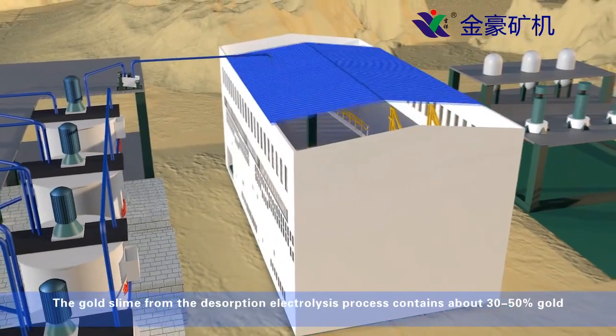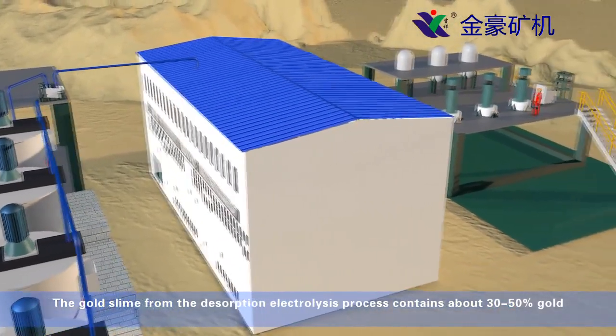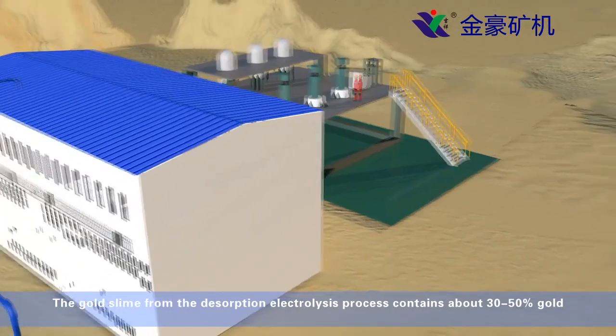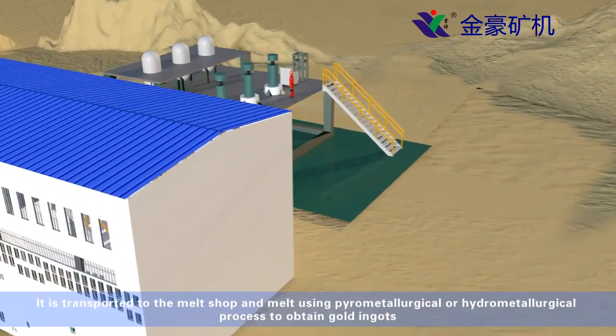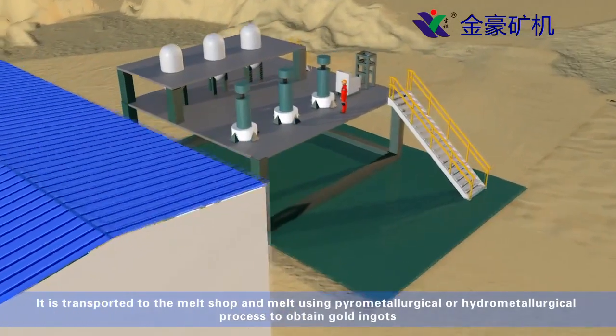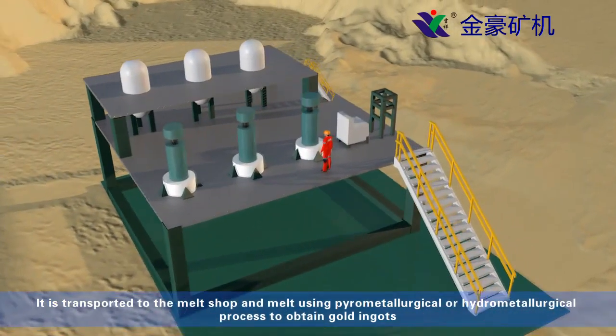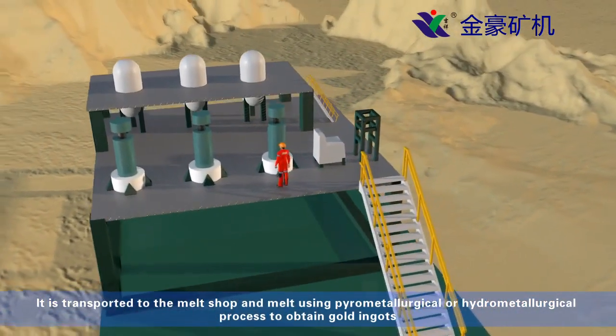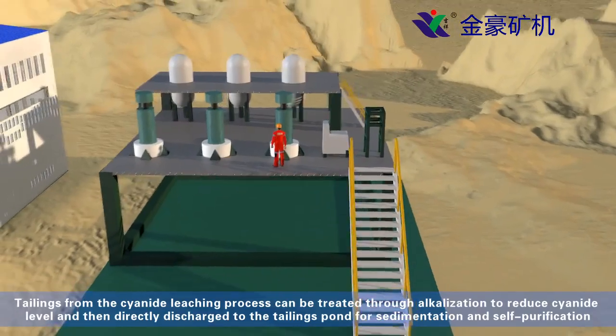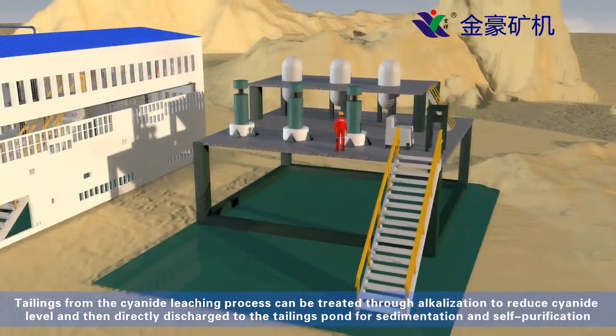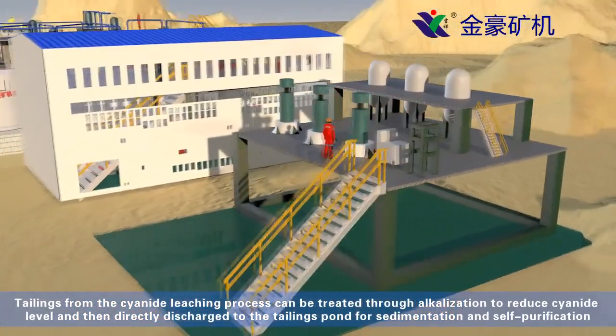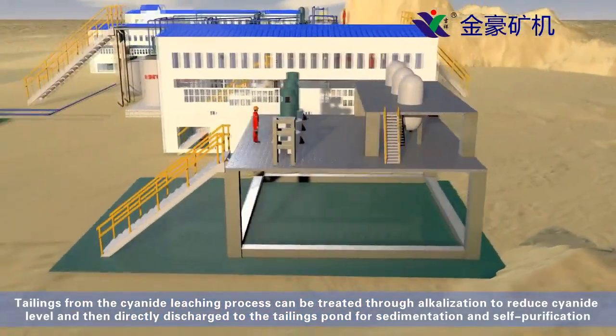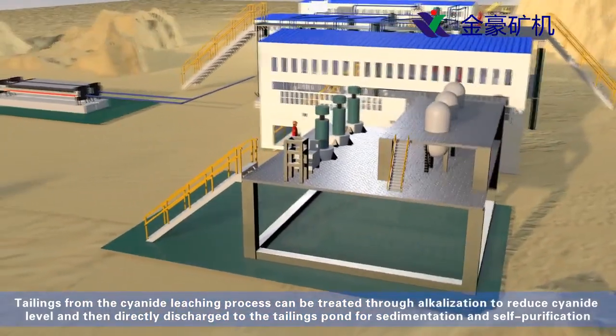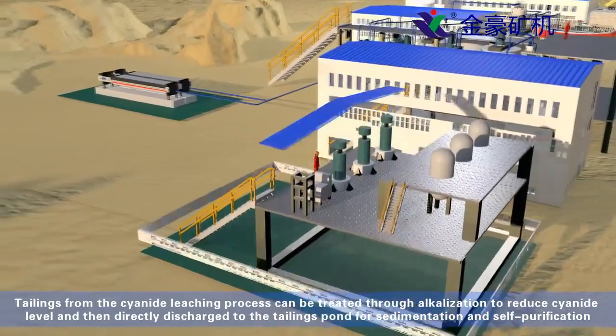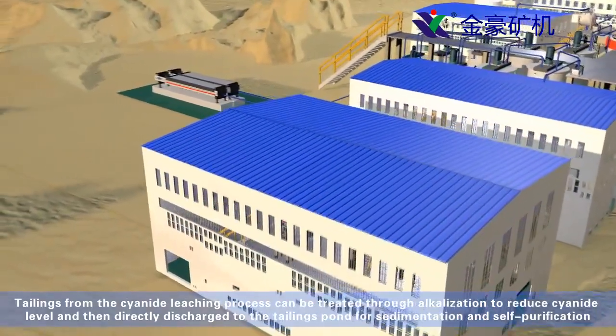The gold slime from the desorption electrolysis process contains about 30 to 50% gold. It is transported to the melt shop and melted using pyrometallurgical or hydrometallurgical process to obtain gold ingots. Tailings from the cyanide leaching process can be treated through alkalization to reduce cyanide level, and then directly discharged to the tailings pond for sedimentation and self-purification.